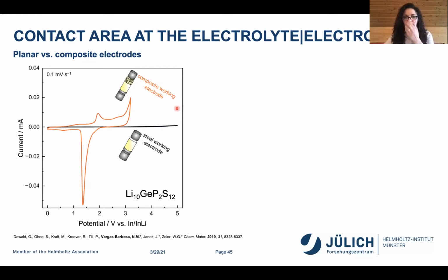to 5 volts. But other studies of cycling thiophosphates against cathode active materials, looking a little bit more carefully at the interfacial chemistry of thiophosphates with oxide-based materials, suggested that they are actually not stable up to these potentials. And the question is, well, can we determine that beforehand? Yeah. And the thought that occurred to us was to increase the surface area.